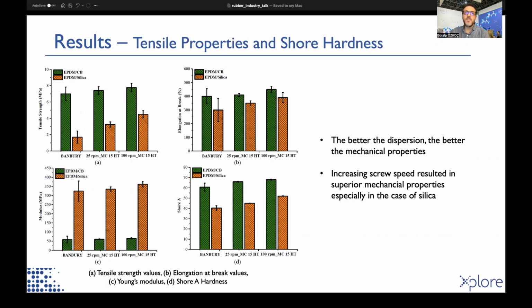As Banbury and microcompounder were compared, the difference obtained for silica was more significant than that for carbon black due to the better dispersion. Additionally, the scatter of the data obtained from the microcompounder was lower than that of Banbury due to better homogenization of the sample batches, as discussed in the dispergrader test results. A similar trend was also observed for elongation at break values.